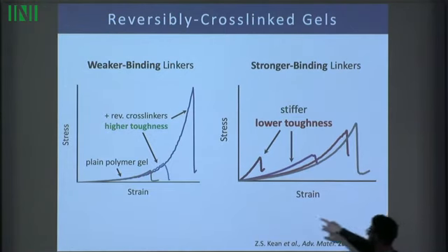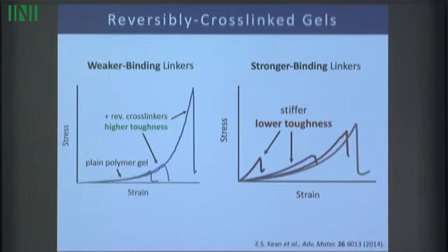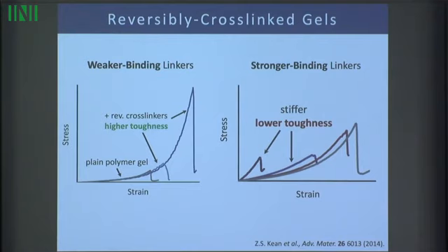So again, here's the intrinsic material shown here. And as I add more of these strong binding reversible linkers, I actually end up changing the modulus. So the slope of the stress-strain curve gets steeper. It's a stiffer material. And it becomes more brittle because actually it fails at a lower strain. Okay? So that's not desired. That's exactly what we don't want. We do want the one on the left-hand side.